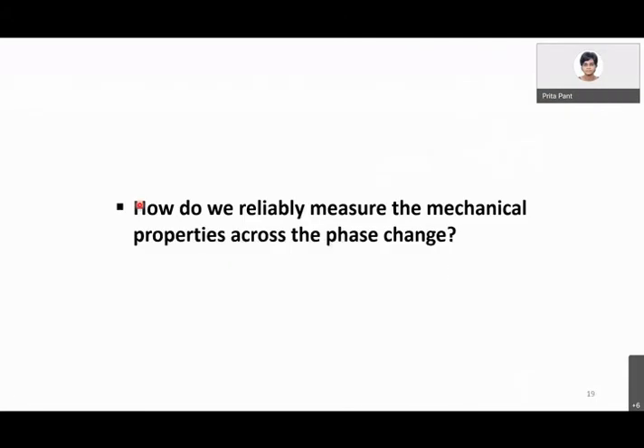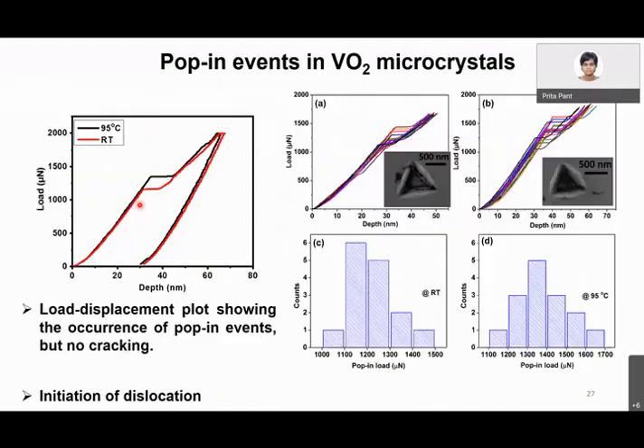And the other question I had was, does the sample plastically deform during indentation at this 10 micronewton and 25 micronewton load? Would plasticity play any role in the phase transformation? I'm thinking in terms of shape memory transformation, where people don't like plasticity because the interface relationship gets disturbed, and the going back and forth of the transformation gets disturbed. You showed some very nice cycling studies on your films where you could repeatably cycle. So I'm wondering, this indentation being very localized with a high local load, would it induce plasticity, and what role would that play?